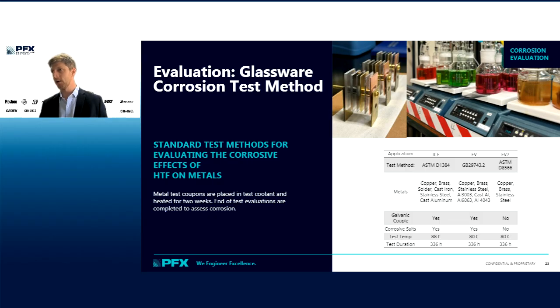What we're looking at here is an ASTM D1384 bundle with copper, solder, brass, steel, cast iron, and cast aluminum. These bundles are then placed into a vessel that contains coolant. They're heated to a specific temperature. They may or may not include corrosive salts to accelerate the rate of corrosion. And then they're held for 2 weeks.